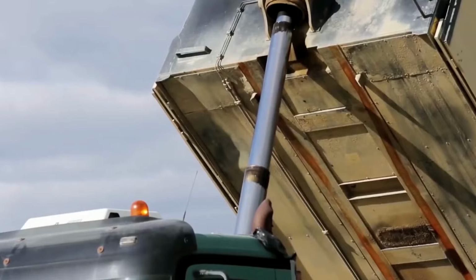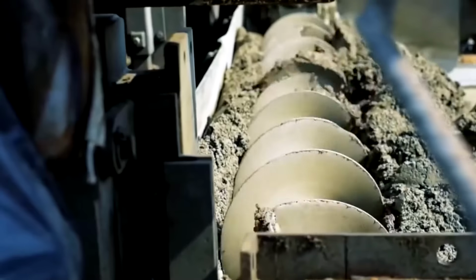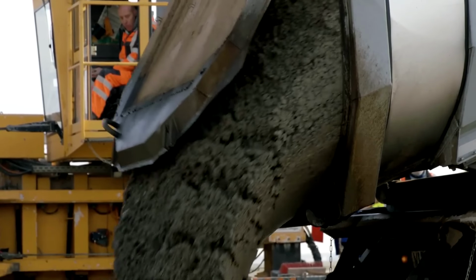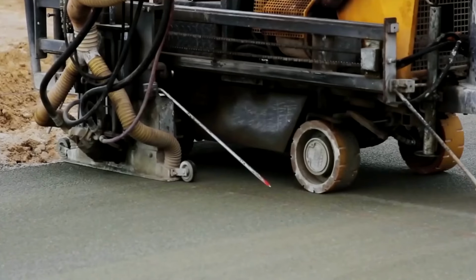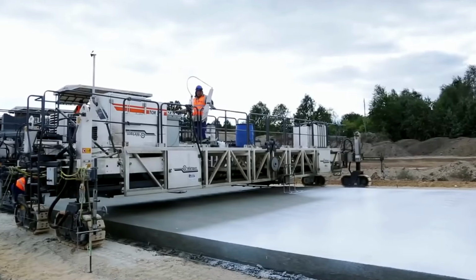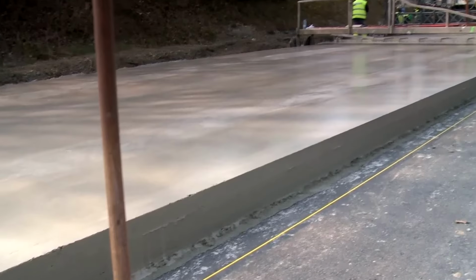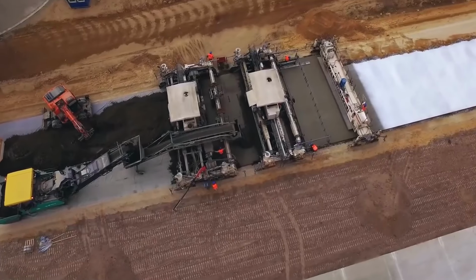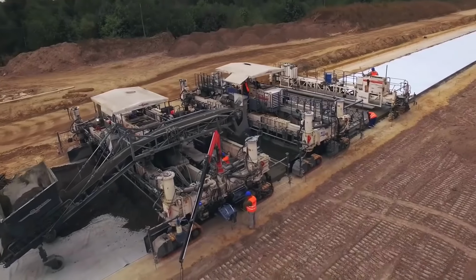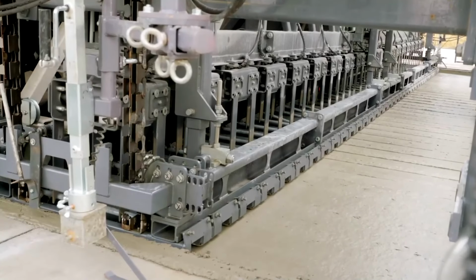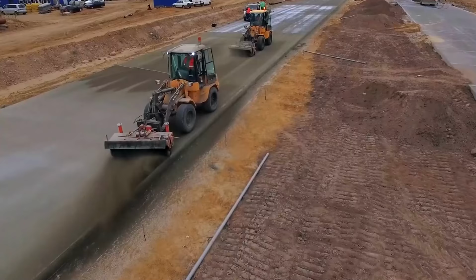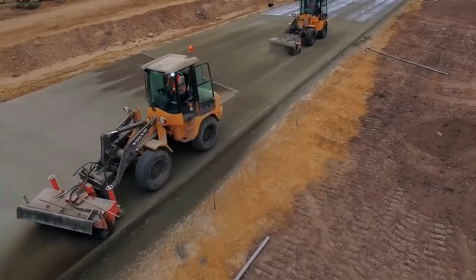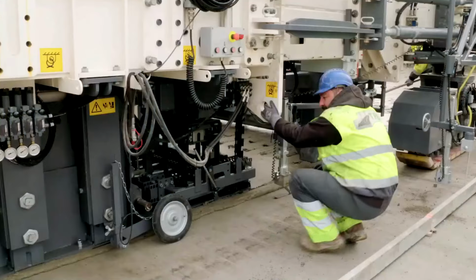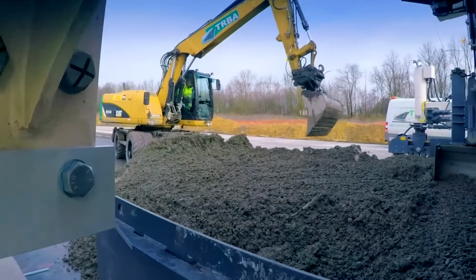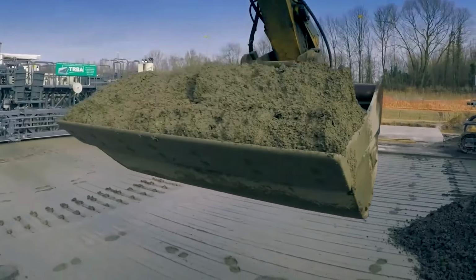Inside the unit, an internal auger system spreads the material evenly across the full width of the road. High-frequency vibrators operate continuously to compact the concrete, forcing air bubbles to the surface to ensure uniform density. A shaping mold at the rear then presses the mixture to exact design dimensions, strictly maintaining thickness and cross-section. The entire process is guided by a laser-controlled system, guaranteeing precise smoothness and slope down to the millimeter. With such continuous operation, the complex mechanism builds dozens of meters of roadway in just a few hours.